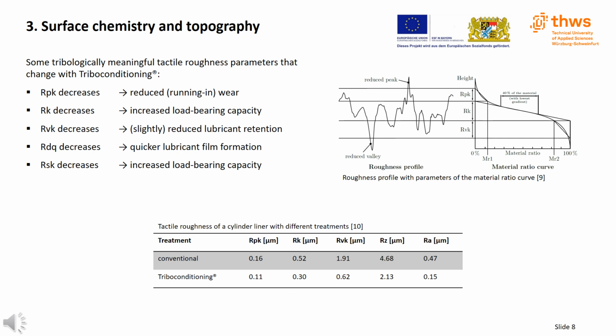The table below shows some tactile roughness parameter values on a cylinder liner. Here, conventional treatment is compared to triboconditioning. It is evident that the roughness values from the material ratio curve, as well as classic roughness values Rz and Ra, are reduced due to triboconditioning.